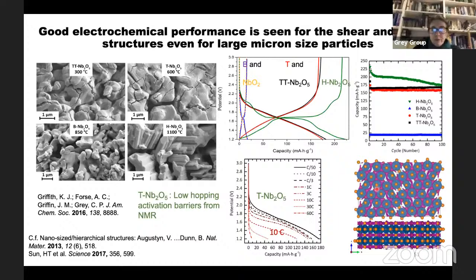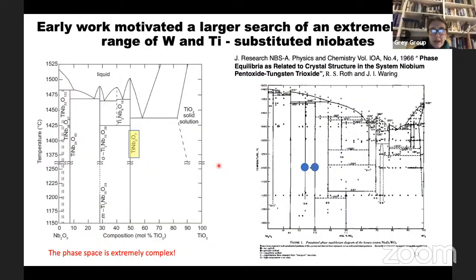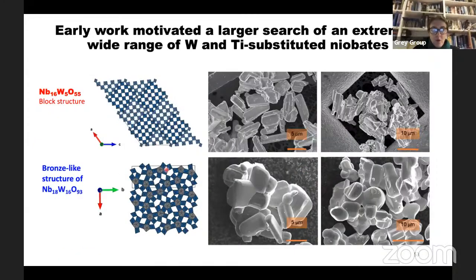So one of my former PhD students, Kent Griffith, spent a lot of time looking at lots of different materials, and he found that some of these niobates were really very high rate, even when there were these very large particle sizes. And so then he went through and looked at a whole variety of different titanium niobates and tungsten niobates, and identified 2 tungsten niobates, one that was a block structure and one was a bronze structure, and that he then tested them in these battery applications. And you can see they have very large particle sizes.